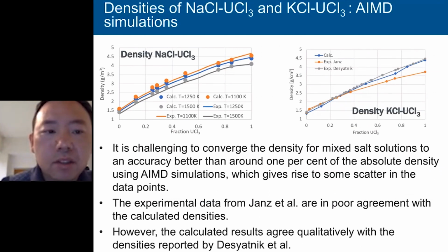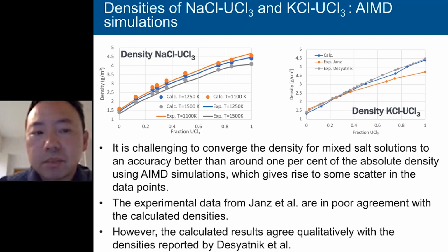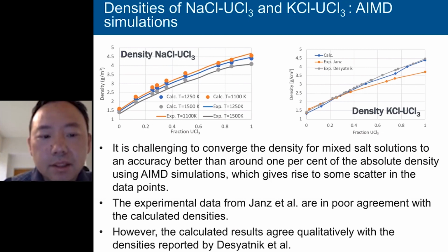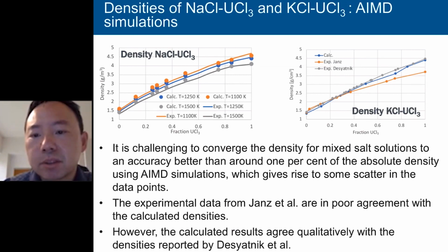Now we go to the binary systems between the actinide and the salt. Here we look at both the sodium chloride and uranium chloride system, and the potassium chloride and uranium chloride system. David mentioned that it's very challenging to converge the density for mixed salt solutions to very high accuracy, so there's some scattering in these plots. You can see that they're not perfect, but I think they're good enough. For both cases, the Ab-Initio MD agrees perfectly with the theory from one of the groups, which are shown as the purple lines.